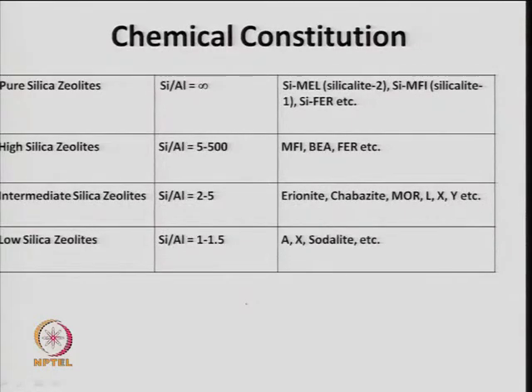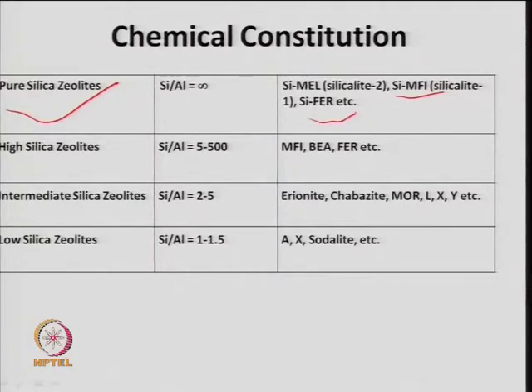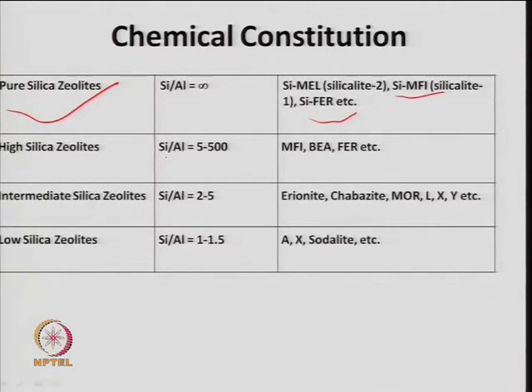The chemical constitution of zeolite — the silica-aluminum ratio — can range from very high to very low. Pure silica zeolite has a silicon-to-aluminum ratio of infinity — named as silicalite, Si-MEL type, Si-MFI type, Si-FER (ferrierite) type. High-silica zeolites such as ZSM-5 type have silicon-to-aluminum ratios between 5 and 500, including ZSM-5 (MFI), beta zeolite, ferrierite, etc.